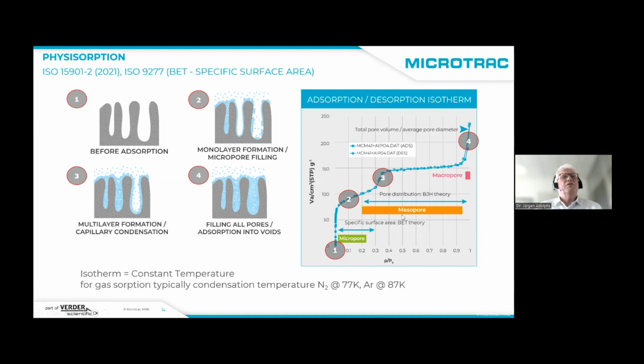So there are two regions, more or less, which are mostly interesting. This is the region of the formation of the monolayer, because from there we can calculate the specific surface area. That means the surface area as a function of the dry mass of our sample, according to the Brunauer-Emmett-Teller theory, for example. And another region is quite often very interesting. This is the pores, the micropores or mesopores, where we are interested in the pore size and the pore volume. This is typically done with the so-called BJH theory, the Barrett-Joyner-Halenda.